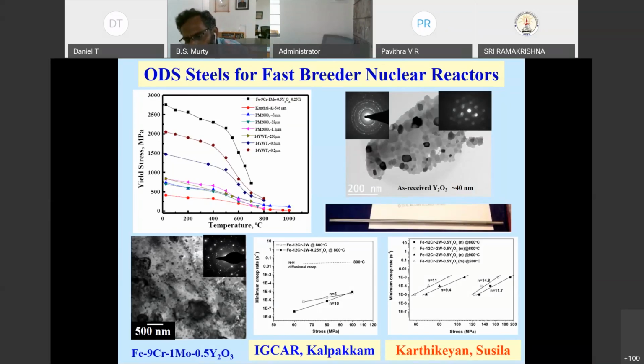And one such example I wanted to give is, again, being a metallurgist, we work a lot on steels, and some of the special steels that people are making now are called ODS steels, oxide dispersion strengthened steel. That means I take a steel and put some oxide particles into it, yttria nanoparticles. When I put nanoparticles into steel, the steel gets a very high creep resistance. That means high temperature resistance. These are being used for fast breeder reactors.